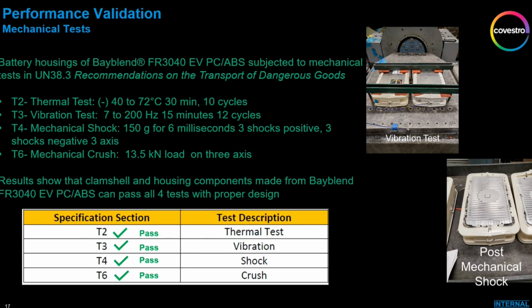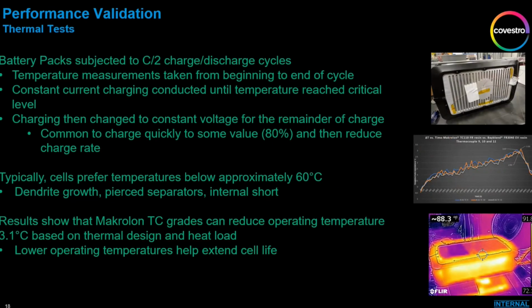So running those tests on these packs with the Bayblend material, we found that the materials were able to pass the requirements and were undamaged during the testing. The test itself requires that you do not have anything open up in the pack. You are not able to access live elements. And it also specifies that there is not catastrophic failure. So in both those criteria, we met them in all of these tests and were able to pass. So we have good confidence that if a component is designed from the Bayblend FR3040 EV, it can meet the requirements and pass these tests.